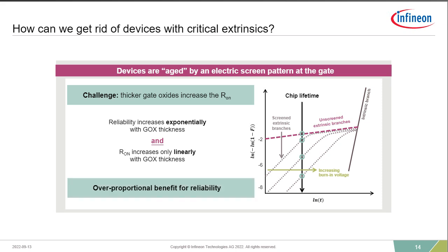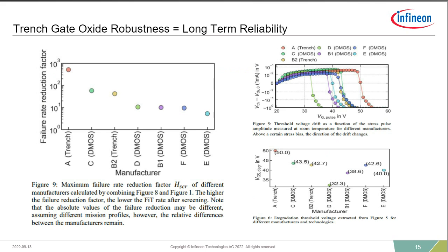And there is a test that we've done in a study that Ohio State has done as well, where you can compare the long-term robustness of the gate oxide structure and therefore the long-term reliability of devices in a particular test. So what you do, and marketing people like to talk about little dots on the screen here as an example, but as you look at this chart on the right, you can see my cursor, you're seeing basically the gate being hit with different voltages. So they're starting at 20 volts, then increasing to 30 volts and 40 volts.